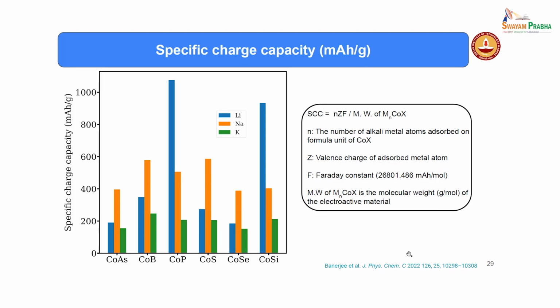So you can clearly see that for lithium, you can see more than 1000. The batteries that we are using generally have a specific capacity of about 300 milliampere hour per gram. I am saying this only about the anode, but the 300 is reported for the overall cell. So here I am considering only the anode, but this anode material has more than 1000 milliampere hour per gram, which is very good news for us, that these materials have good potential to be used in lithium ion batteries. Similarly, for sodium, the majority of them fall in the range of 400 to 600 milliampere hour per gram, which is also very good.